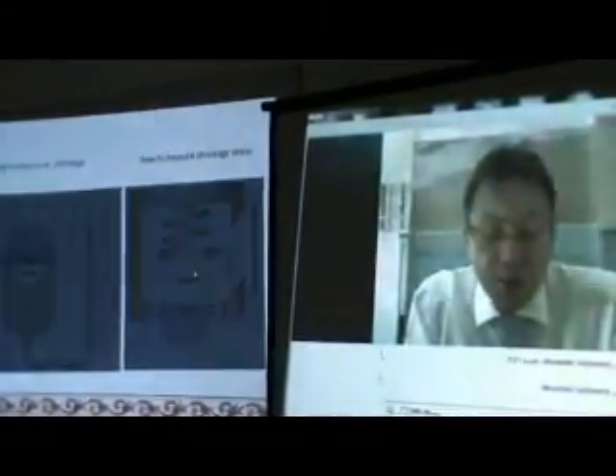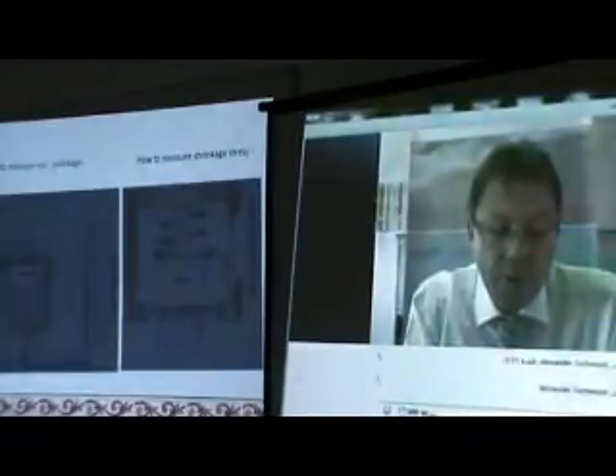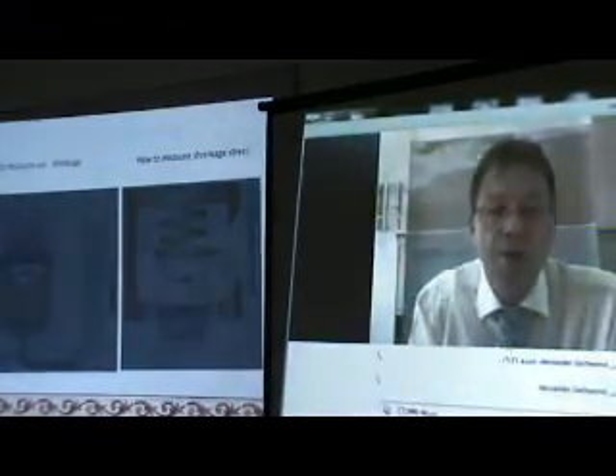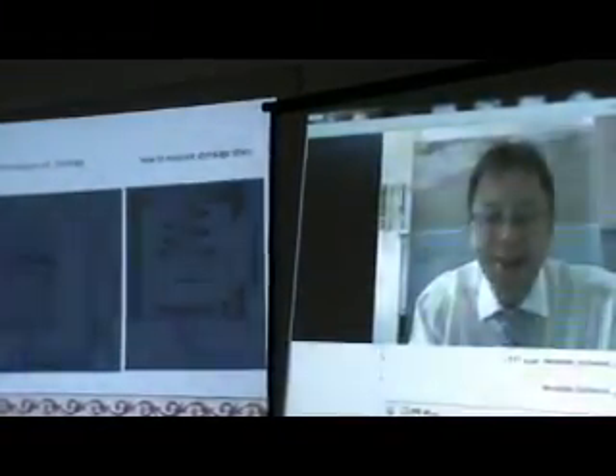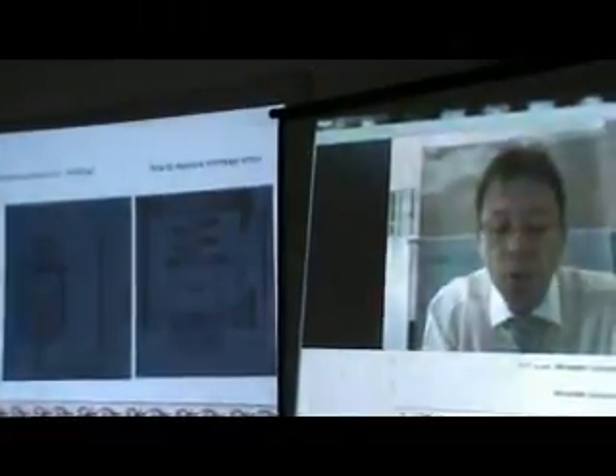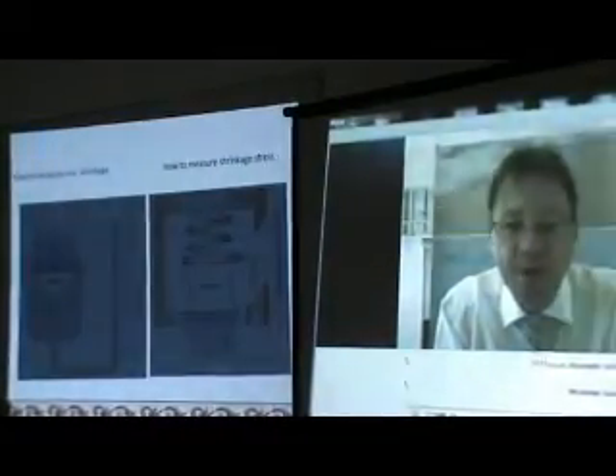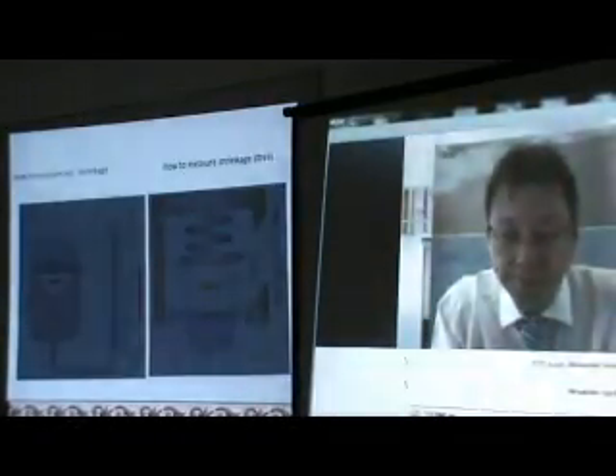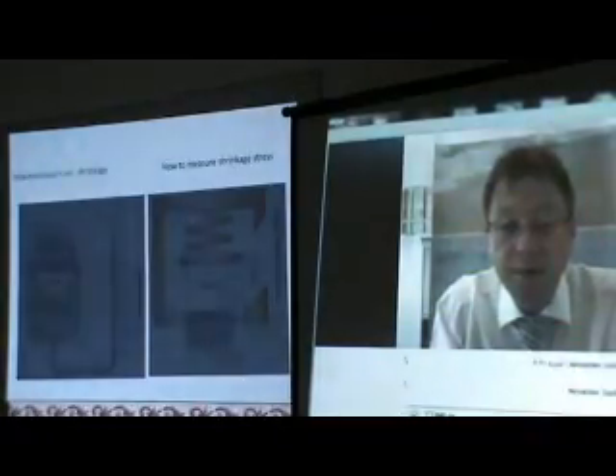On the right side, one addition to this. Now you see here on the left side, about volumetric shrinkage, that this does not really reflect reality, because your restoration is actually adhering to the dental walls. Here you have only one bonded surface, the surface with the glass plate. All the rest, there is no bonding, there is no resistance. But in reality, you may have 2, 3, 4 bonded surfaces.